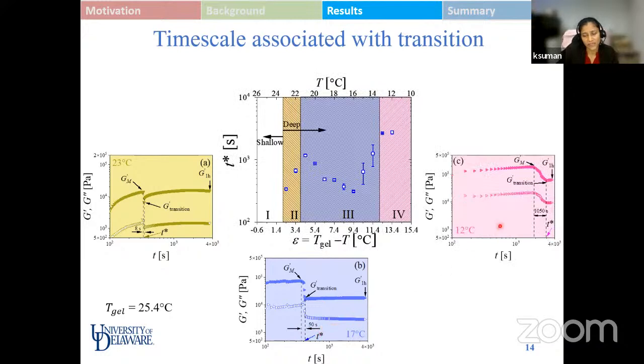On performing the same experiment at very low temperatures, which is 12 degrees and very far away from the gel point temperature of 25.4, we see that the transition is occurring gradually and it takes longer to transition, followed by a plateau value over here. So the transition takes around 1000 seconds to get completed at very low temperatures.